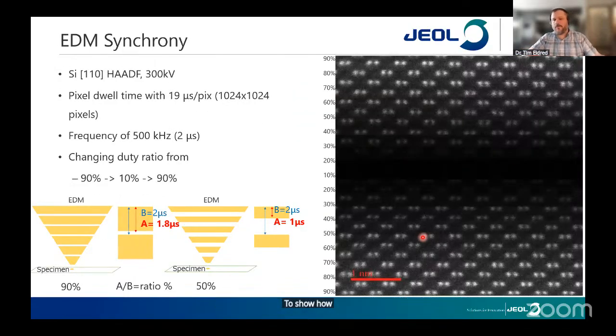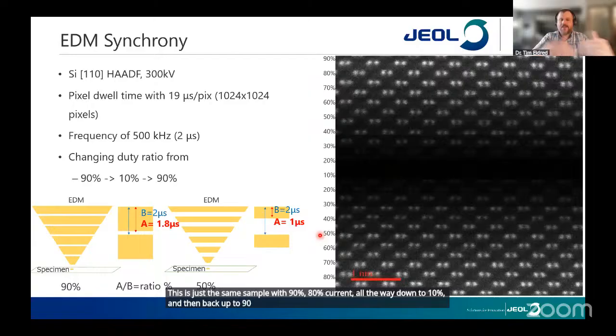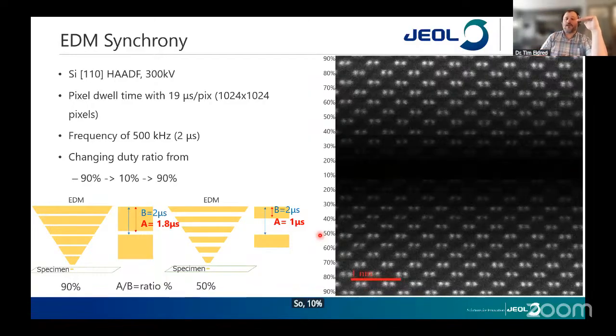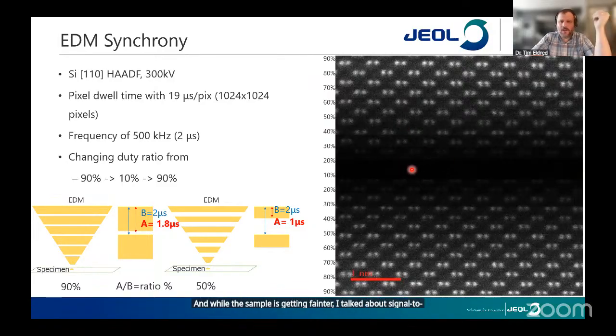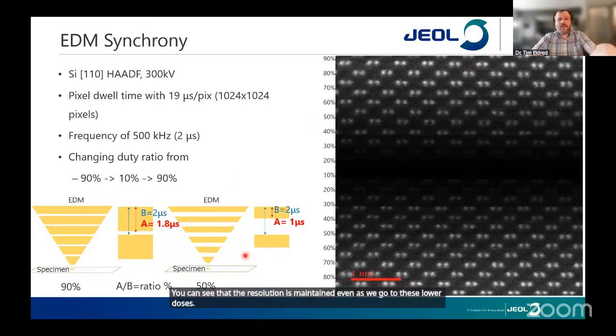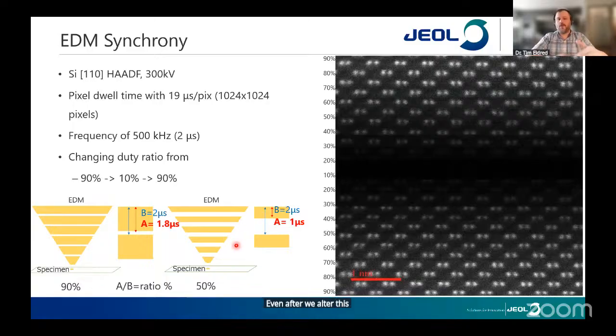To show how they've been able to do it, this is with EDM. This is just the same sample with 90%, 80% current all the way down to 10% and then back up to 90%. So 10% drops in dose, exact same sample. And while the sample is getting fainter, I talked about signal to noise earlier, you can see that the resolution is maintained even as we go to these lower doses, even after we alter this duty ratio, the on to off.